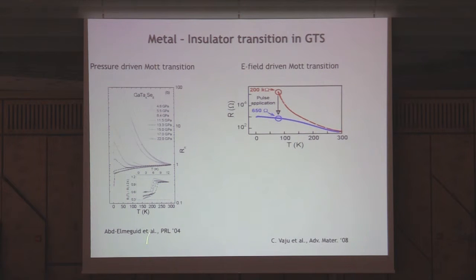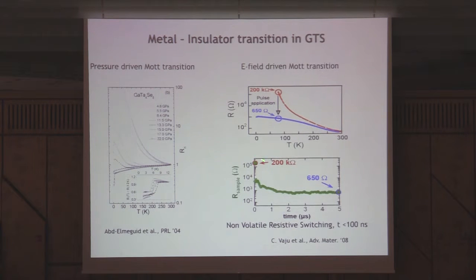Okay, so after this, a very interesting discovery was made by the group in Nantes, where they start with one of these compounds, which looked insulating, and then applying a strong electric pulse, managed to change the resistance by orders of magnitude. Moreover, they found that the change was non-volatile. They apply a strong pulse, the resistance changed, and then it remained, you see, almost 3 orders of magnitude lower than the initial value. Moreover, if you apply a reverse field, you can undo this effect. So immediately you think of applications. So this can be applied as a non-volatile memory, and the switching time can be as low as to be in the nanoscale regime.